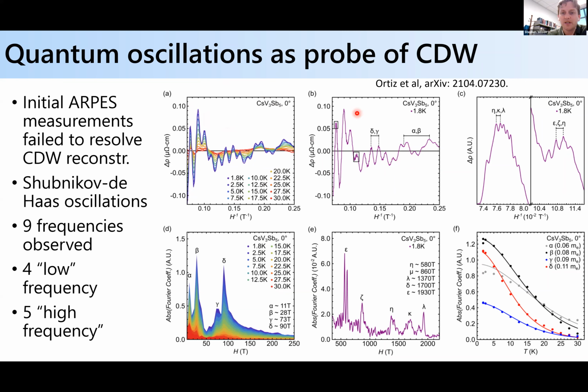But if you look at just the low temperature data, here are oscillations, and you can see there are many different frequencies, many different harmonics encoded in this. In fact, if you look at this little box here and blow it up, as well as this box here, you can see there are also very high frequency components dressed on top of the lower frequency oscillations. So we can take this spectrum and do the Fourier transform, and I'm going to break it up into two different windows. This window here I'll call the low frequency window, and this window here I'll call the high frequency window.